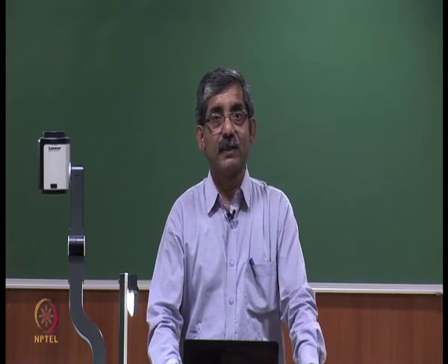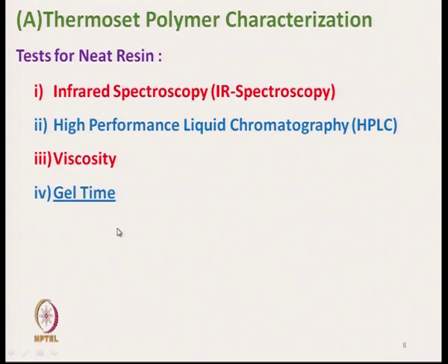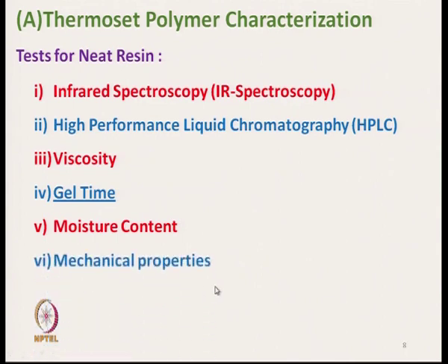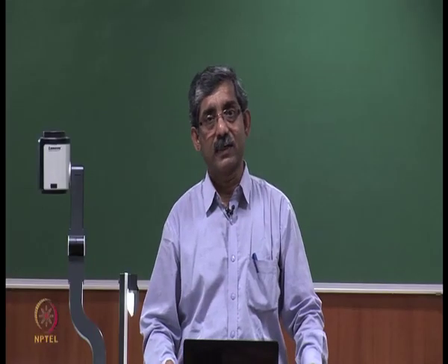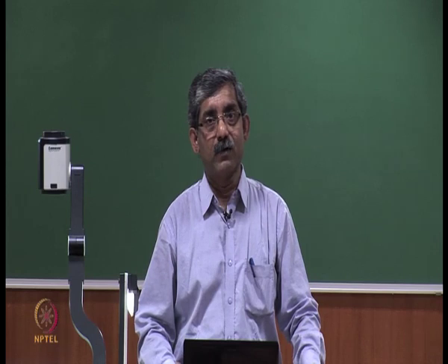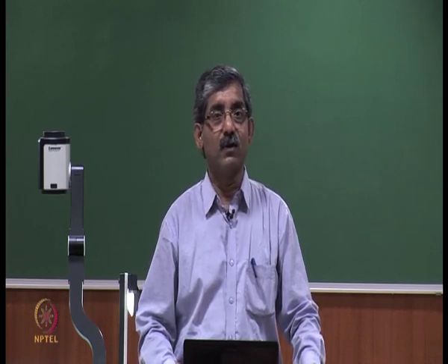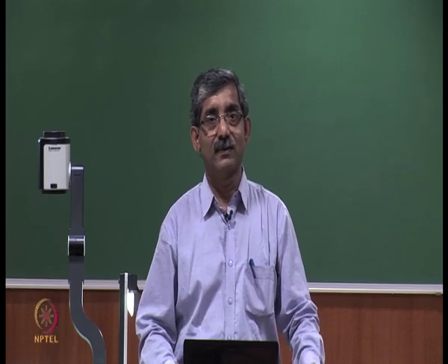Next method is gel time characteristics. Gel time measurement indicates the solidification time. Moisture content, which is an important characteristic. Mechanical properties are important, that is the strength properties. Density. So, these are the characteristics which are important both for thermoset resin and also for thermoplastic resin. And this gel time, which is underlined, this characteristic is only for thermoset resin.